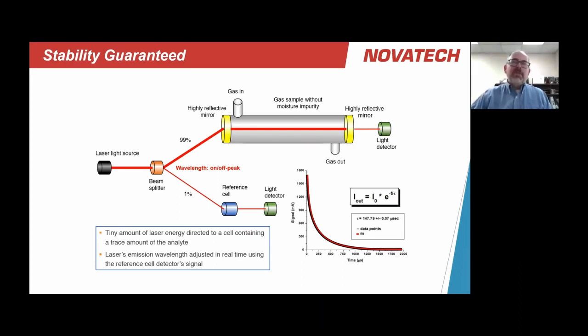One other thing worth mentioning is that these analyzers will also use what's known as a reference cell. And that's really a function of the fact that we're trying to measure at very low concentrations. It's important to know that we're looking at the right area, that we're emitting our energy at the correct wavelengths. So the light from the laser is split between the sample cell and the reference cell. A small portion of it goes through the reference cell.